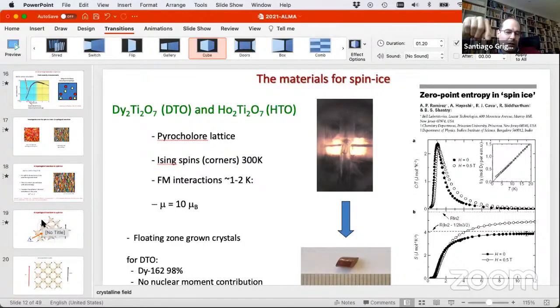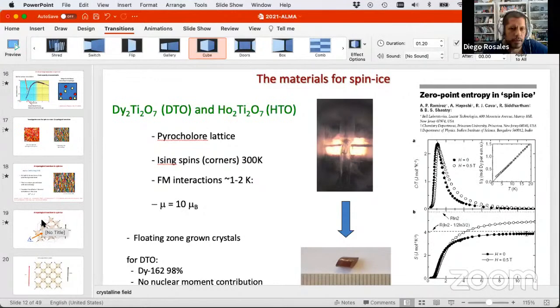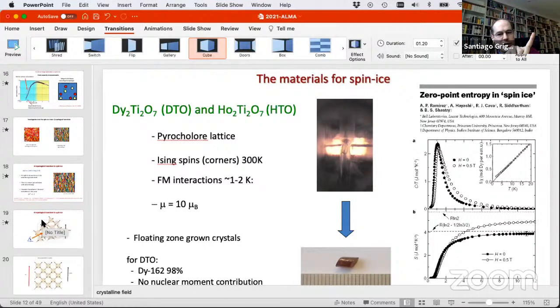And there's one other Kasteleyn transition that we haven't looked for in spin ice, where you put a field along 1, 1, 1. If you look at the pyrochlore along 1, 1, 1, it's like stacking Kagome lattices and triangular lattices. What you do with the field is first freeze the triangular lattice, because those spins are fully polarized in the direction of the field, and the others are not. So you reach the regime of what people call Kagome ice, which is some sort of ice in the Kagome planes. Then if you tilt the field, people say there's also a Kasteleyn transition on the Kagome plane. Yes. But we haven't looked for that.